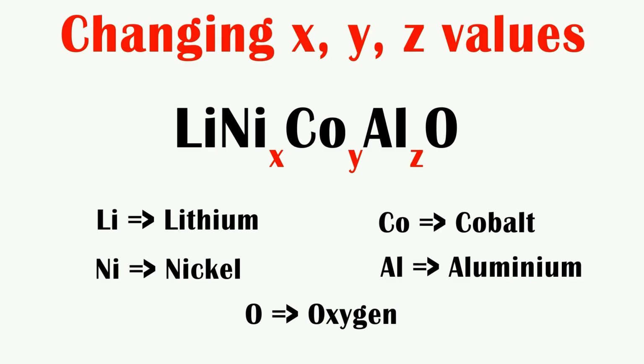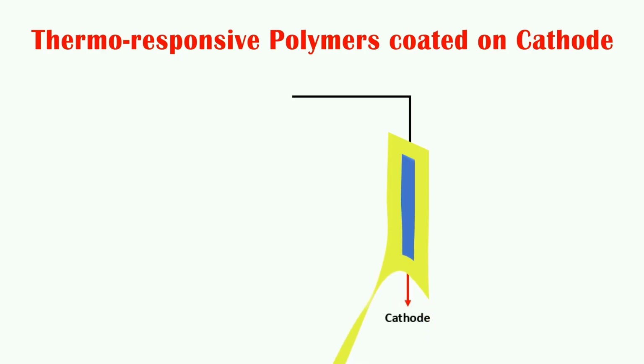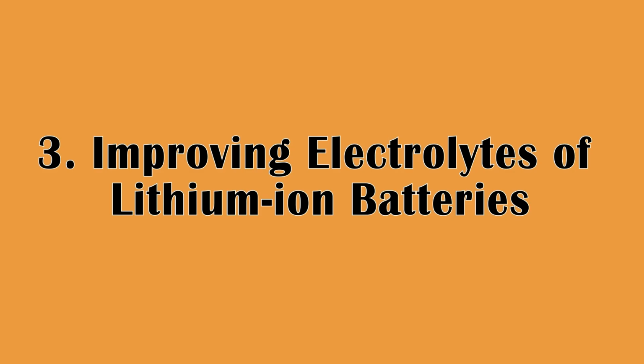The release of oxygen by these lithium metal oxides can be reduced by changing the stoichiometric ratios of the metals or the use of the metal combinations in the lithium metal oxides as cathodes. Here also thermal responsive polymers are coated on the cathode to shut down the battery when a certain threshold temperature is reached. Third, improving the electrolytes of the lithium-ion batteries.